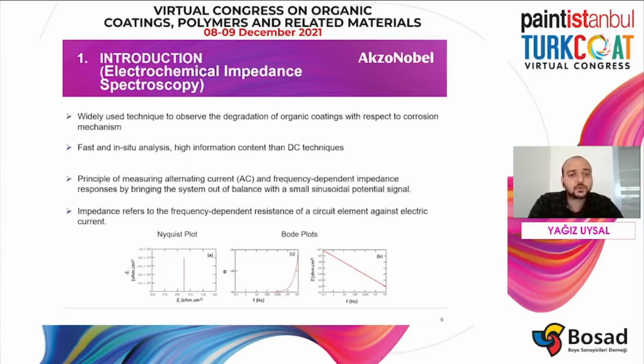Electrochemical impedance spectroscopy is a widely used technique to observe the degradation of the coatings with respect to corrosion mechanism, and it's fast and non-destructive, and it gives more information than the DC techniques. This technique works on the principle of measuring alternating current and the frequency-dependent impedance responses by bringing the system out of balance with a small sinusoidal potential signal.